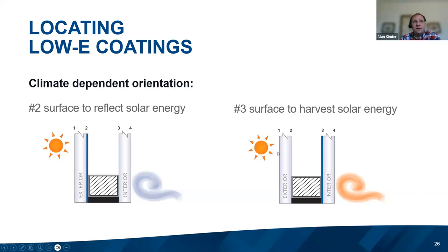There are a few select low E coatings that are designed for number three surface placement. Not overly scientific how to get here. You just turn the insulating glass unit backwards and now all of a sudden you have a number three surface orientation. But with that, we are actually using this for passive solar heat gain in our far northern reaches. So what we see is the sun's energy comes uninhibited through that outboard light, heats up that air cavity, and then you have a low E coating on surface number three. So we have a higher solar heat gain coefficient in this scenario, but we still have a pretty good U value or thermal performance so that we retain that warmer air in that interior space.